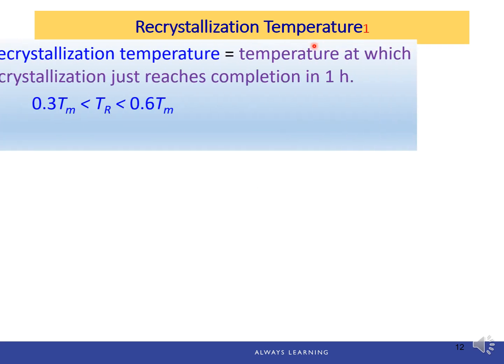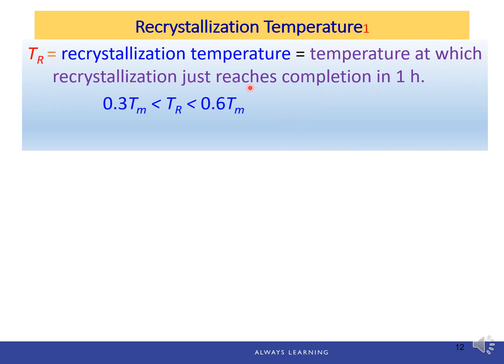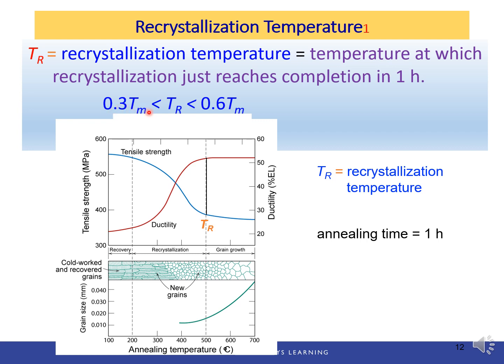The recrystallization behavior of a particular metal alloy is sometimes specified in terms of the recrystallization temperature. It's the temperature at which recrystallization just reaches completion in 1 hour. Typically, it is between 1/3 and about 60% of the absolute melting temperature of a metal or alloy. For example, in this given alloy, I believe it's a brass alloy, based on the annealing diagram, we can see the recrystallization begins here and completes at 500 degrees Celsius. So the recrystallization temperature is about 500 degrees Celsius.